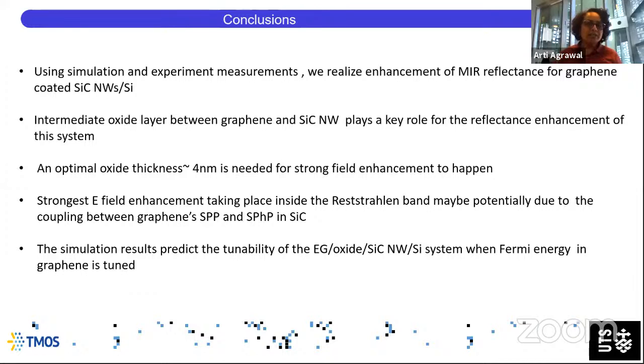In conclusion, using simulations and experiments, we have realized enhancement of mid-infrared reflectance for graphene-coated silicon carbide nanowires. The intermediate oxide layer between graphene and silicon carbide plays a key role in this system, and an optimal thickness is needed for subdiffraction confinement and strong field enhancement. This is likely because of the coupling between the surface plasmon polariton and the surface phonon polariton. We can also predict that we can tune the system by tuning the Fermi energy in graphene.